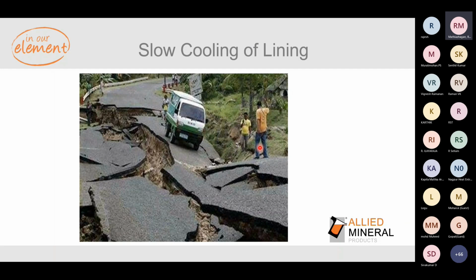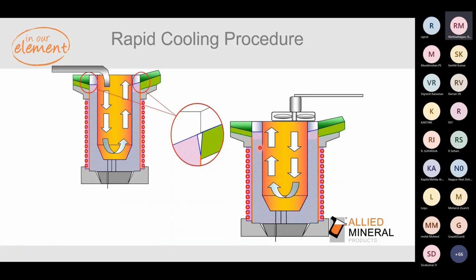So traditionally, we are following slow cooling. There are people actually who put charge also inside the furnace, which is not recommended. If you want to do a slow cooling, just empty the liquid metal out, put a blanket on the top, and let it cool, rather than putting any charge or any scrap inside the furnace. So this will help you a lot. So rapid cooling, this is the way we normally recommend.